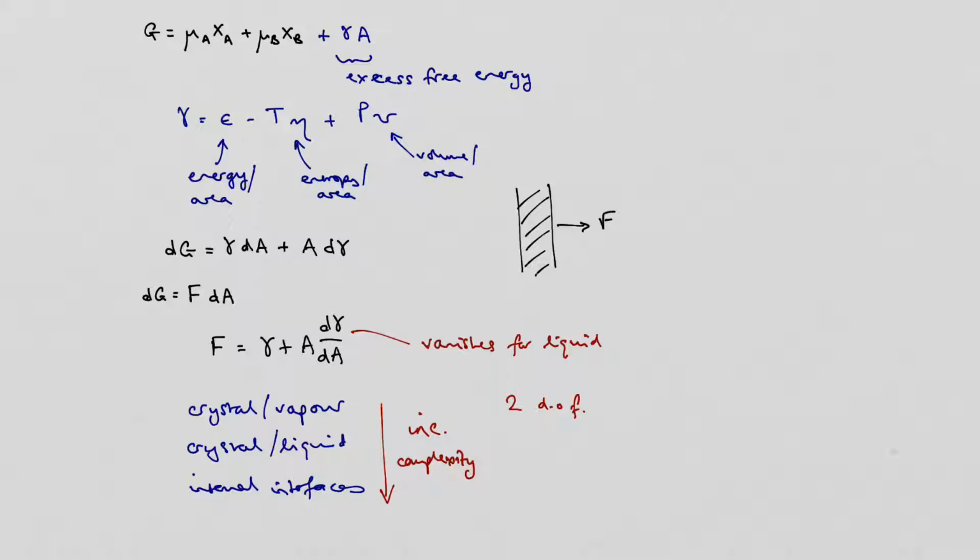So over here I've got this crystal, over here I've got this crystal, but I've said nothing so far about the orientation of the interface between the 2. It could be like that, or like that, or like that. So there's a planar orientation there that requires another 2 degrees of freedom. So I end up with 5. So there are 5 degrees of freedom there when we're talking about grain boundaries. That just shows you how these things are more complicated, if you want to discuss these things.